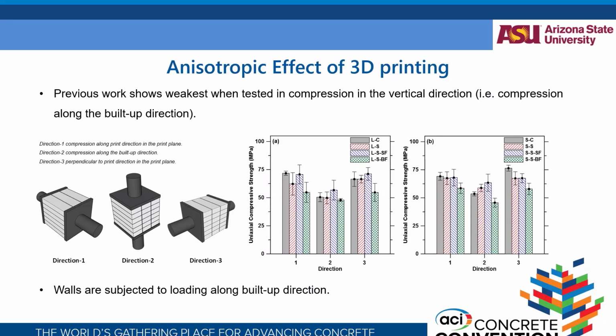For the structural part of it, we have done some anisotropy quantification for different mixes and different layer heights. This is for one of the works that we previously did. What we have observed is that typically, when you have multiple filament interfaces and layer interfaces, direction 2, which is uniaxial compression along the build-up direction, which will be a typical loading scheme in a wall section, because that will be loaded in this direction. What we usually observe is that for different infill patterns and different printing patterns, direction 2 has a significant reduction in strength compared to direction 1 and 3.